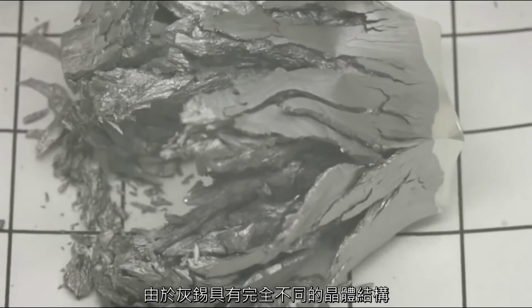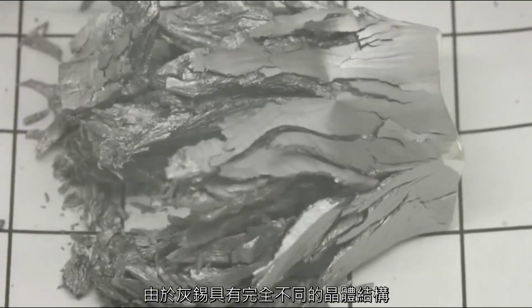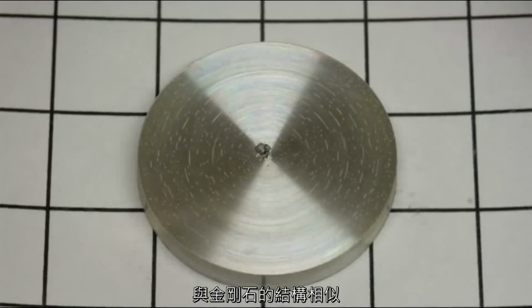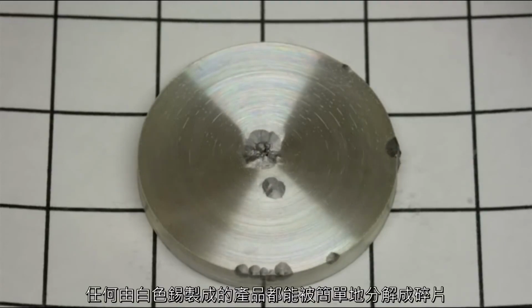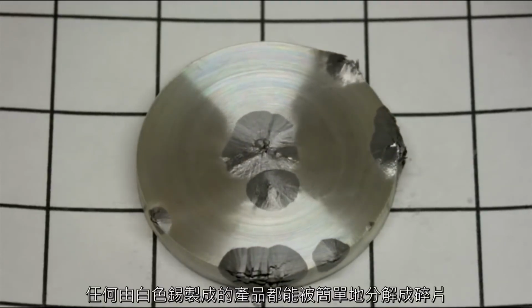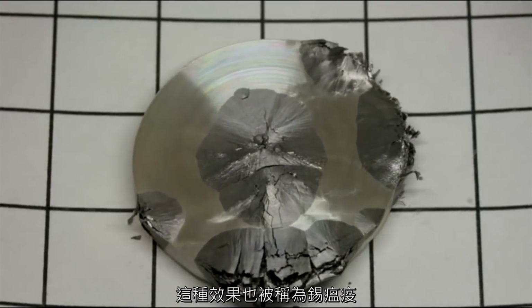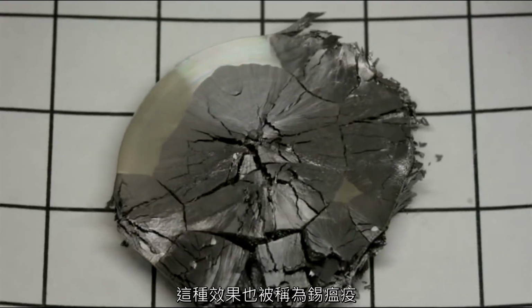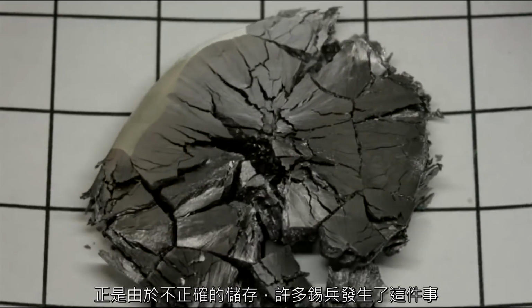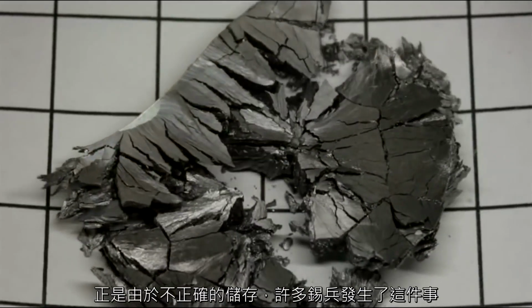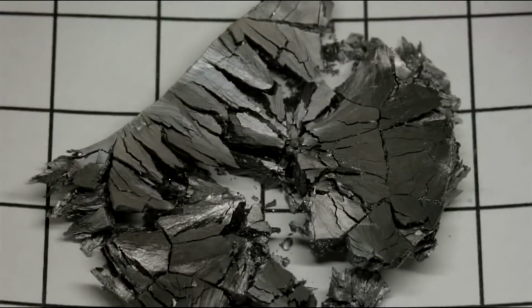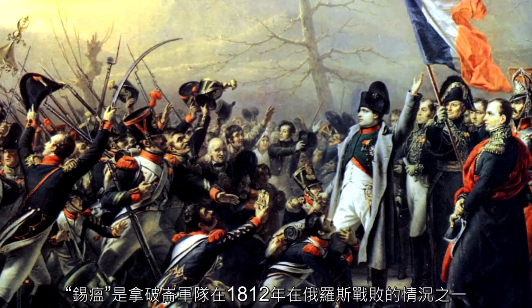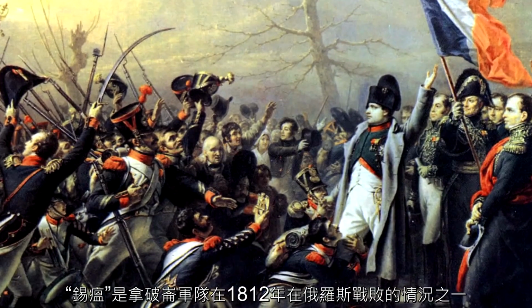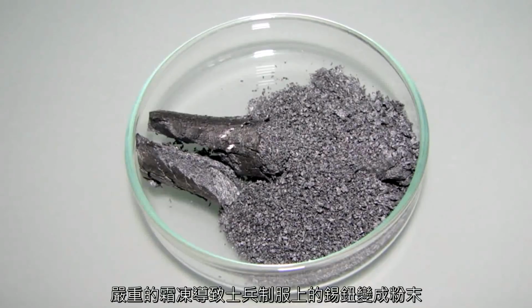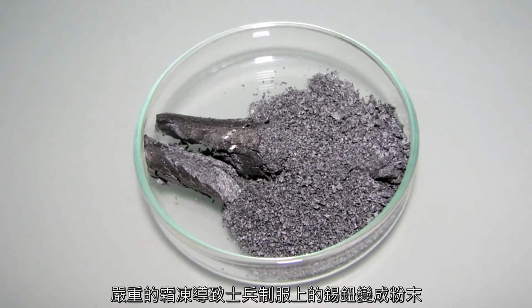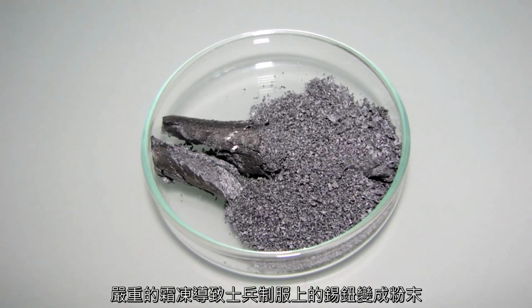Since gray tin has a completely different crystal structure, similar to the structure of a diamond, any product made of white tin will simply fall apart into pieces with this transformation. This effect is also called the tin plague. This is exactly what happened with many collections of tin soldiers due to improper storage. Also, some historians point to the tin plague as one of the circumstances of the Napoleon army defeat. Severe frosts led to the transformation of tin buttons on the soldiers' uniforms into powder.